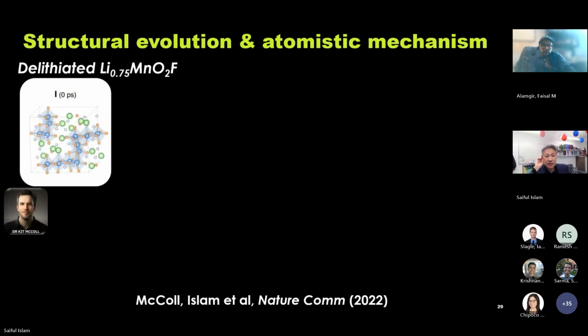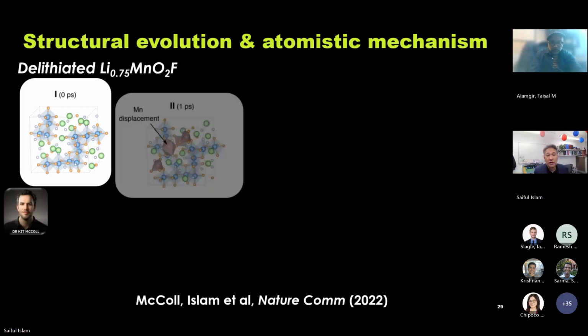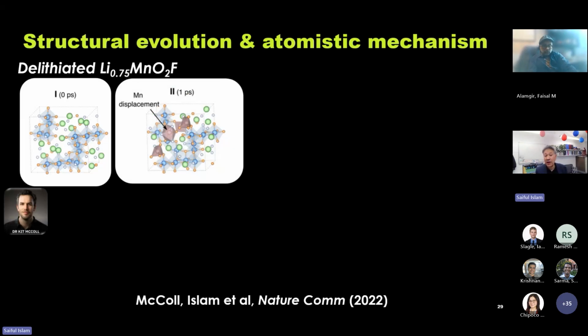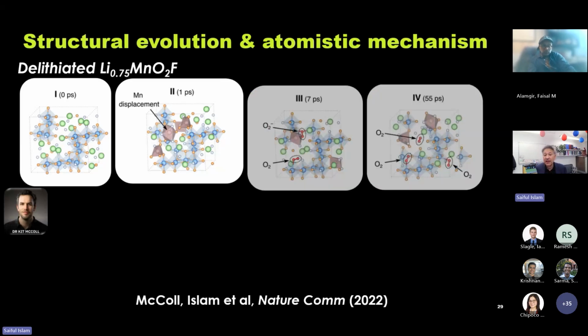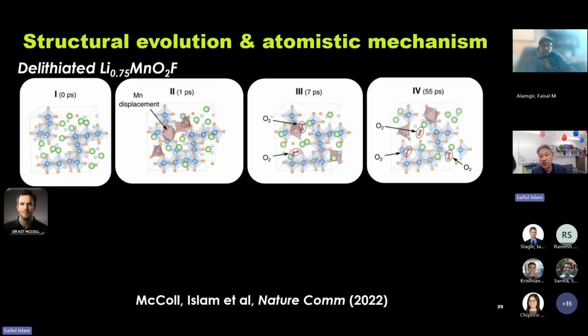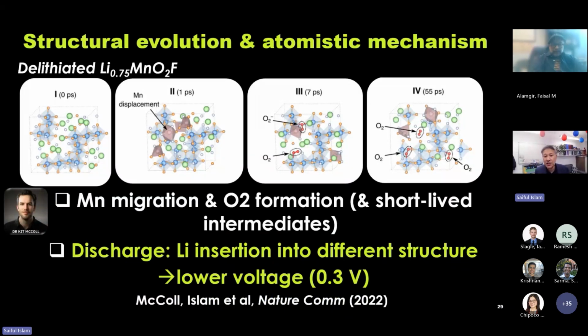So what happens kinetically? So here I'm going to show you snapshots from some ab initio MD at the top of charge from the starting structure on the top left and then the time evolution for our MD simulation. First of all, interestingly, we find manganese displacement first. That manganese displacement leads to some undercoordinated oxygen, and we begin to find some transient dimer species, for example, superoxide, and then right at the end, the thermodynamic product includes molecular O2 in the bulk and displaced manganese. So manganese migration and O2 formation, but short-lived intermediates of peroxide or superoxide. They are not the thermodynamic product.